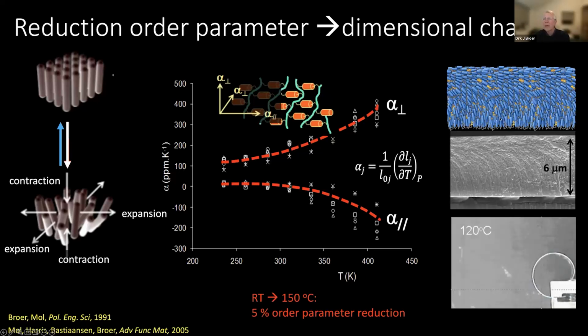if you make a film which has a planar orientation at one side and a perpendicular orientation at the other side, we call this a splayed orientation, and you can see it basically if you take the film, you break it, and you look with the scanning electron microscope to the cross section, you see more or less a resemblance of the molecular orientation. Then you will be dealing at the top with this negative thermal expansion, at the bottom with this very positive thermal expansion, of course. And if you start heating the film, you have made your first actuator in this case. Well, this is temperature, but it can also be done by light or by electrical field, or you can even absorb other materials into the system to create similar effects.